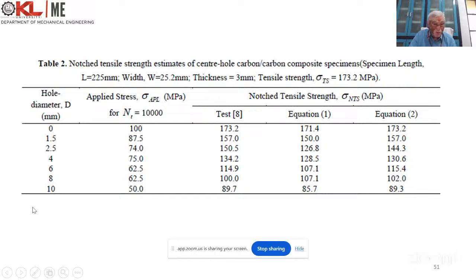If you drill a 10 mm diameter hole, for 50 megapascal stress, the test failure stress data is 89.7, whereas the assessment is 85.7. So the acoustic emission is indirectly helping us to assess the residual life of the composites.